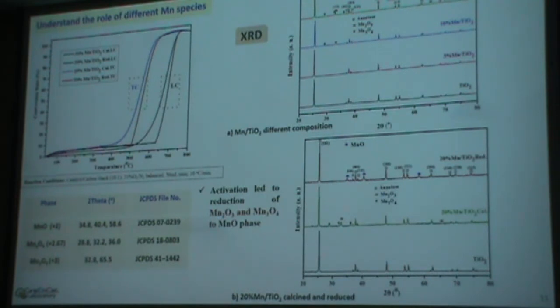Reduced means we used hydrogen for the reduction. We compared the XRD analysis of different percentages of Mn and the reduced catalyst. It shows that as the Mn loading increases to 20%, the crystallinity of the Mn3O4 and Mn2O3 phases increases quite a lot, and in the reduced sample, most of the Mn3O4 and Mn2O3 is reduced to the MnO phase.